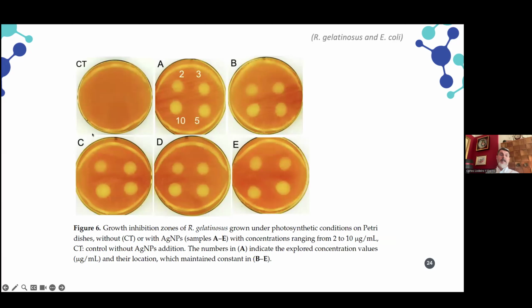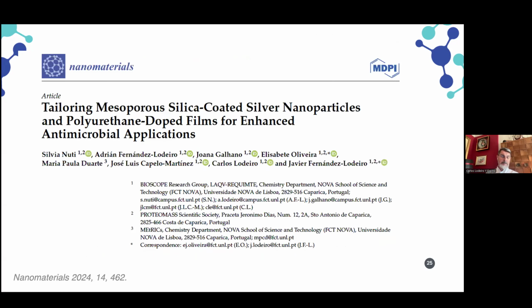And then you can see in the control example there is nothing, so we don't see absolutely nothing. But then when we added the nanoparticles, from 2 to 10 micrograms per milliliter, we start to see the growth of a halo around the nanoparticles that inhibits and kills the Rubrivivax gelatinosus bacteria. So we are also exploring this in contaminated waters, and we are working in this field at this time. However, this is a solution.